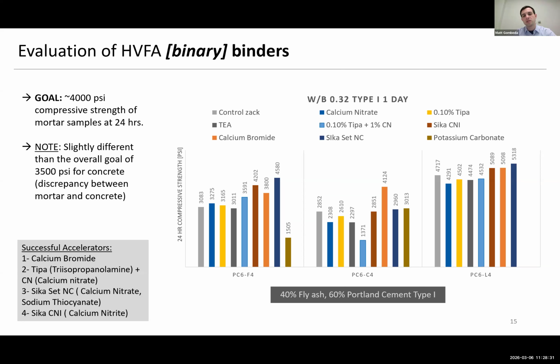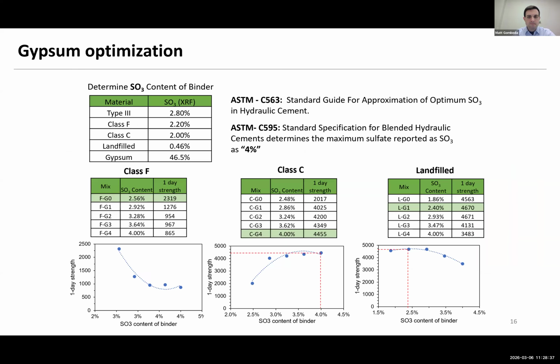And I should also note that this part of the study was done by Penn State in collaboration with us at IIT. One thing that was crucial to our dialing in our strength development was gypsum optimization. So when we're adding more fly ash and we have a reduction in Portland cement, we're losing a little bit of that gypsum content that could help balance chemically the mix. So we're adding back in the gypsum to an optimal dosage to facilitate the strength gain that is most effective with our dosages of cement and fly ash at 60% cement and 40% fly ash, essentially. A little bit of gypsum that we'll add here in addition.